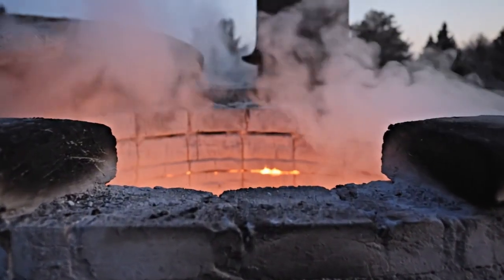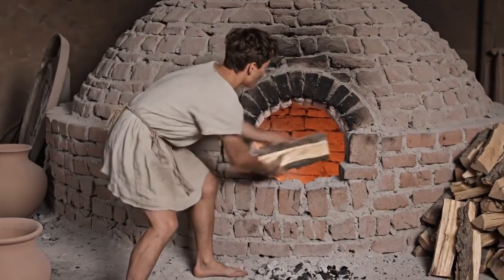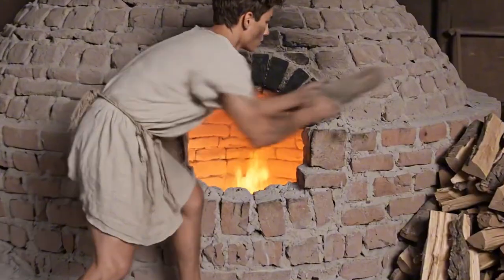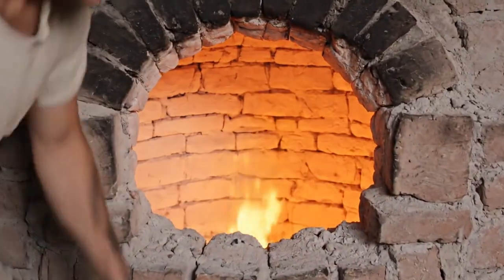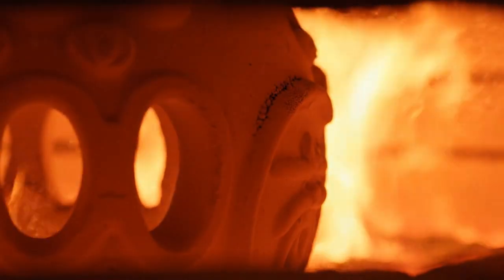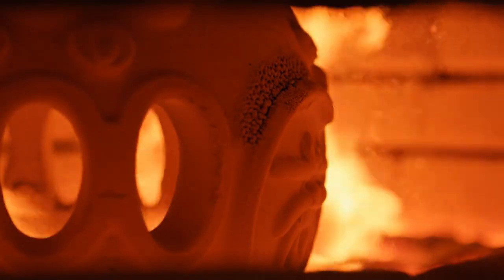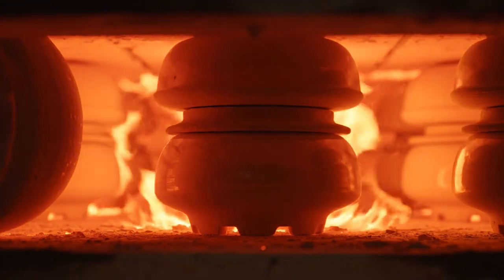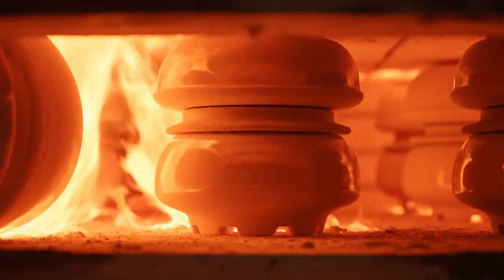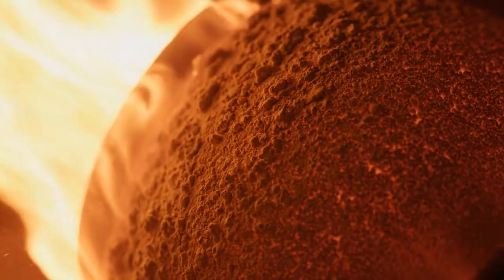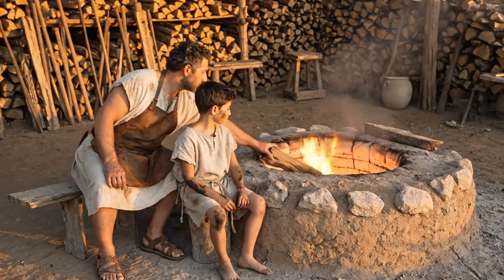This initial phase, called water smoking, takes the temperature slowly up to around 300 degrees. Then the pace quickens. As the kiln climbs past 500 degrees, the clay undergoes a process called ceramic change. The crystal structure of the clay minerals irreversibly transforms, and the material can never again be softened by water. It is no longer clay, it is ceramic. The firing continues upward toward 800 or 900 degrees, where the iron oxides in the clay begin to flux, and the body sinters into a hard, dense, reddish mass. The slip, with its finer particle size and higher iron concentration, vitrifies into a smooth, semi-glossy surface.